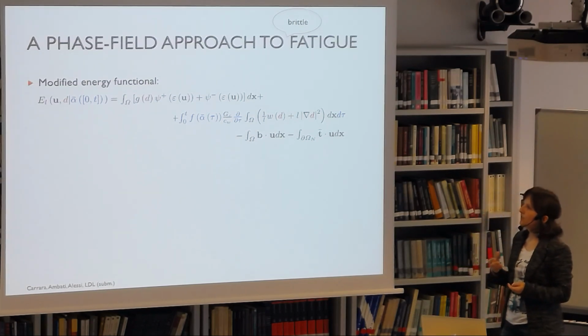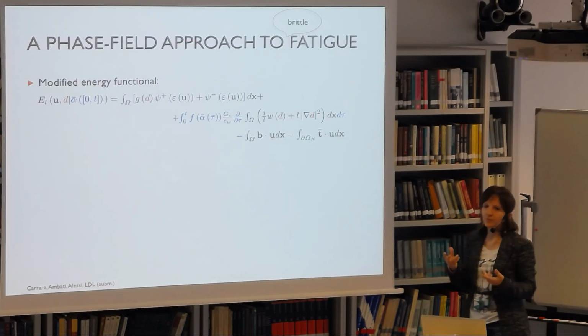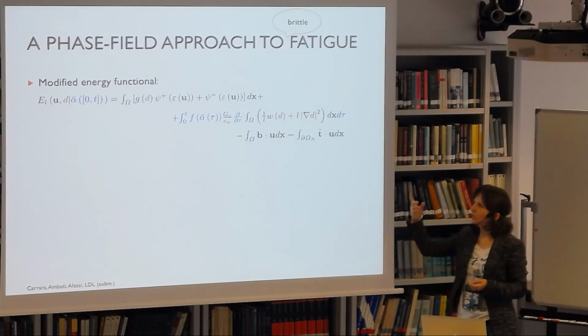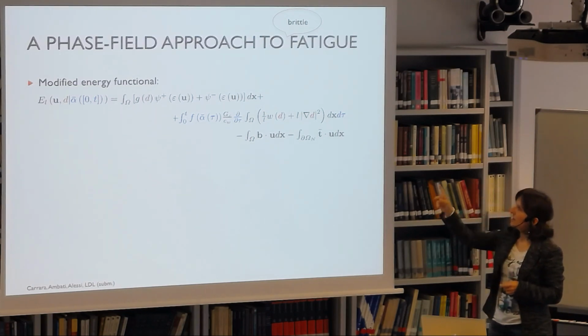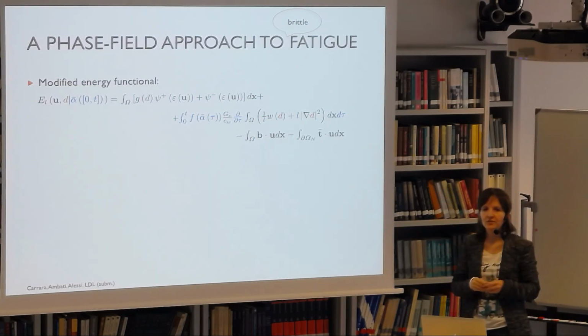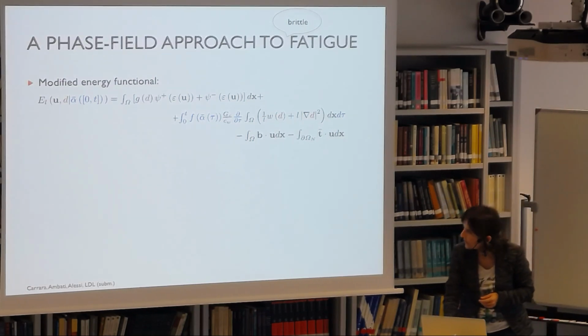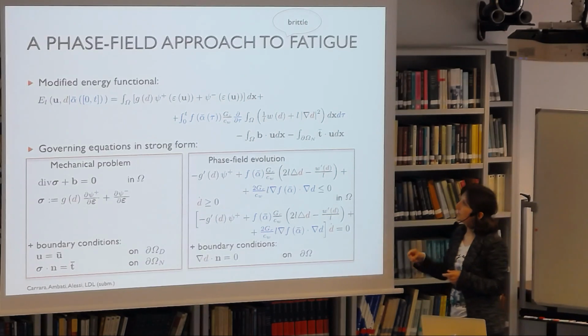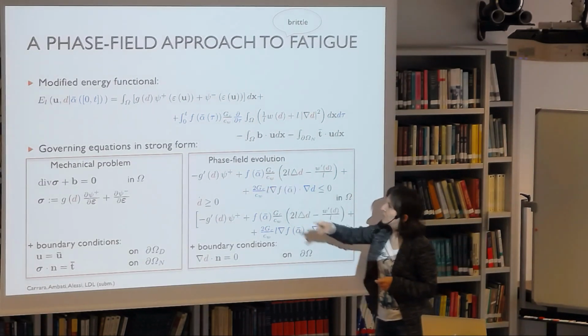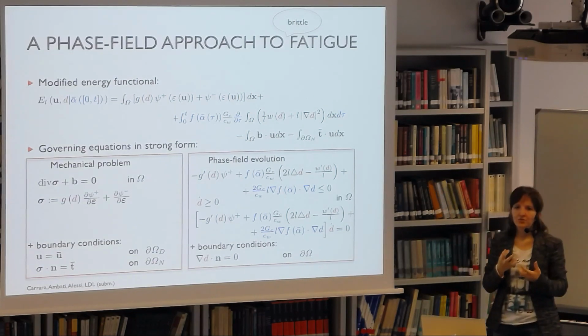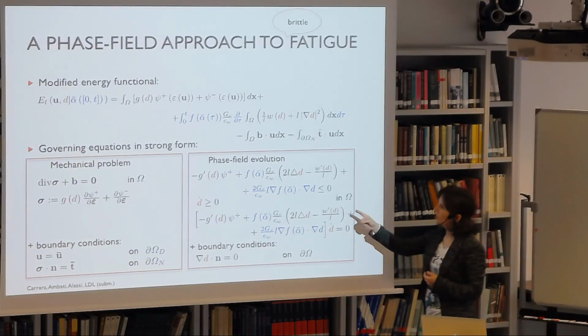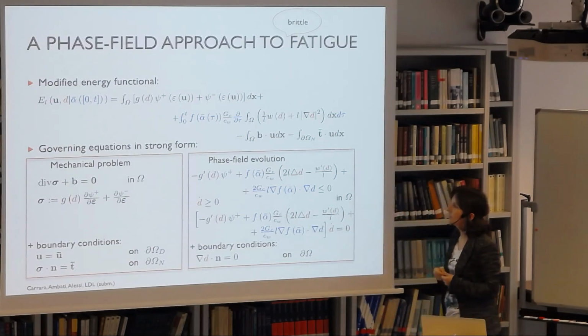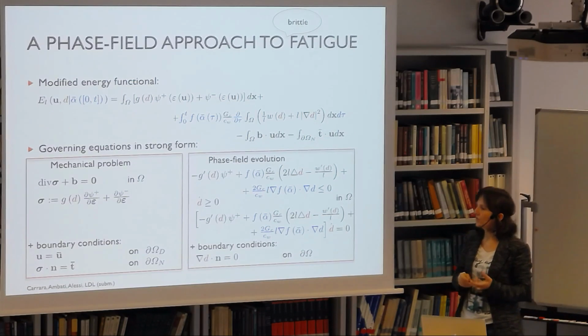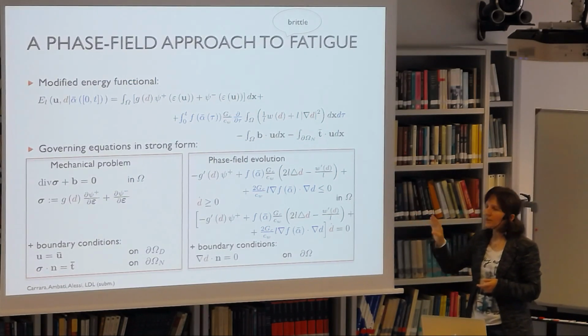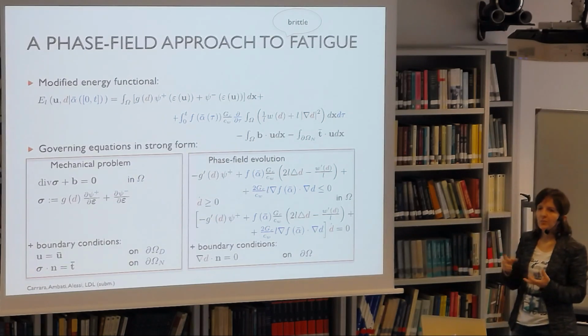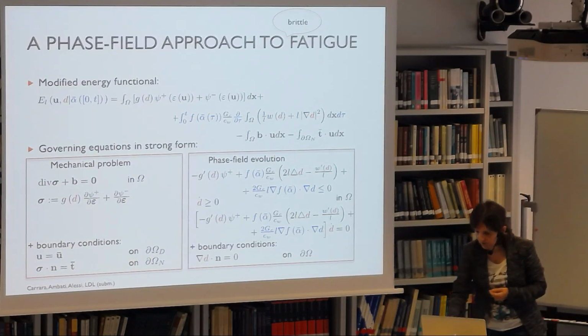What we have is now a modified energy functional where the dissipation, of course, becomes history dependent. So we need to introduce this fatigue degradation function inside the damage part of the integral, and we need to account for the history. So effectively what happens is that this degradation function multiplies the fracture toughness, and so we have a degraded fracture toughness over time, and also we have an additional term that contains the gradient of this function, scalar the gradient of the damage variable or phase field, as you want. So with these relatively minor modifications to the approach, then we can account for fatigue.